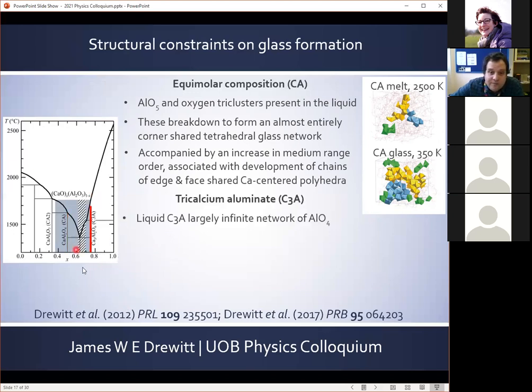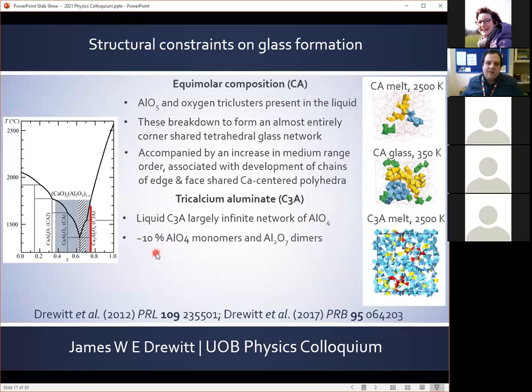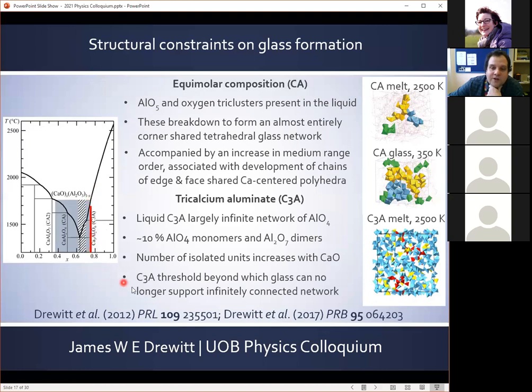For the calcium-rich end member of the glass-forming region, tricalcium aluminate C3A, despite this being a depolymerized composition, the liquid is largely composed of an infinite network of AlO4 units. However, we observe around 10% of unconnected AlO4 monomers and Al2O7 dimers, indicated by these red and yellow units in this simulation model. And we observe that the number of these isolated units increases with increased calcium content. And so this can explain the limit of glass formation, since the tricalcium aluminate composition represents a threshold beyond which the glass can no longer support an infinitely connected network.